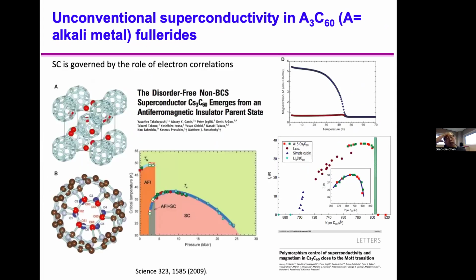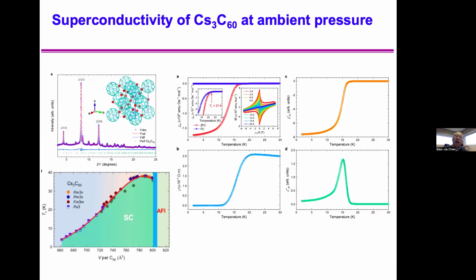This idea actually is not new. You can see that Cs3C60, carbon 60 fulleride, this superconductivity was reported to appear at high pressure, not so high, around 5 kilobar or around 1 GPa. And we made an effort to reach room temperature, ambient condition, ambient pressure. We have a superconducting phase.